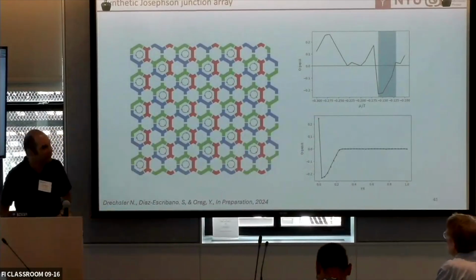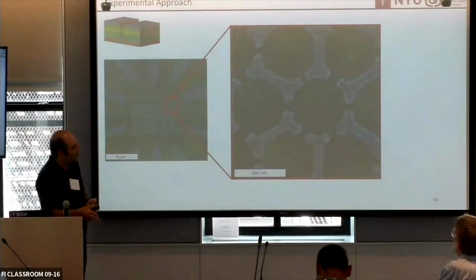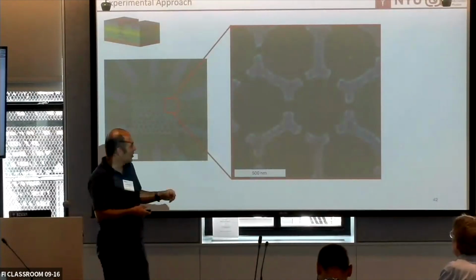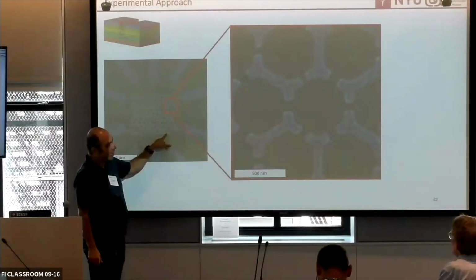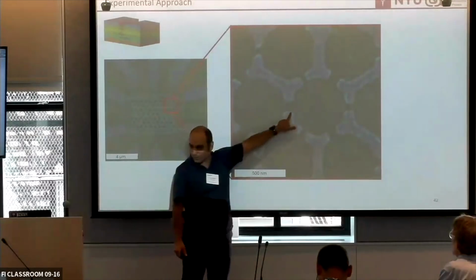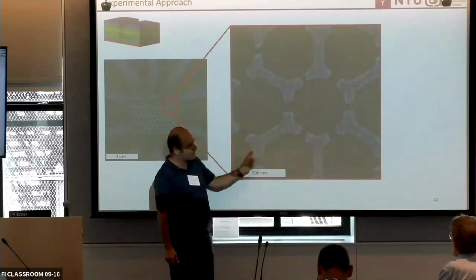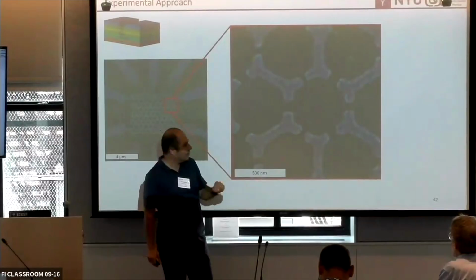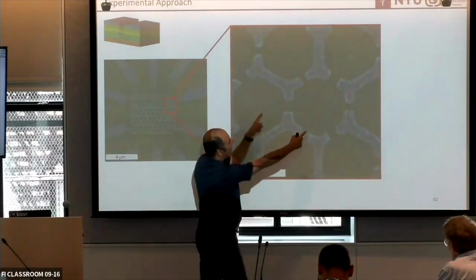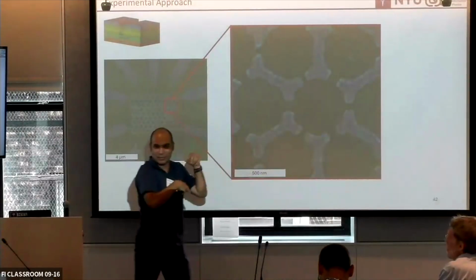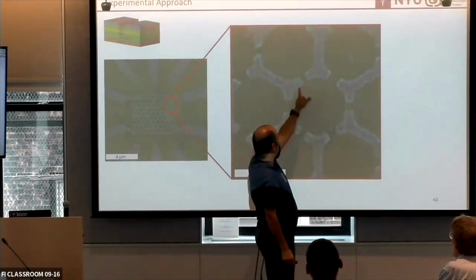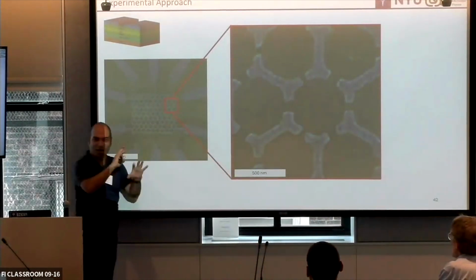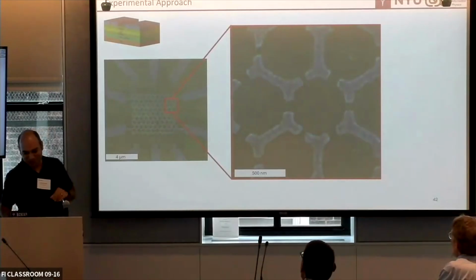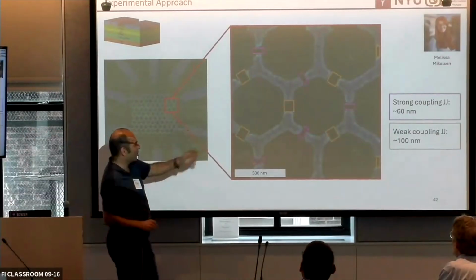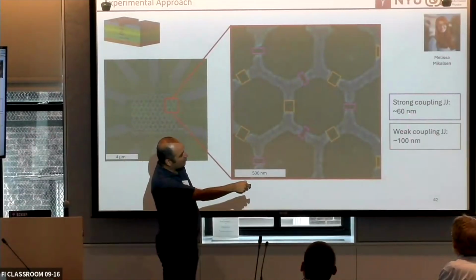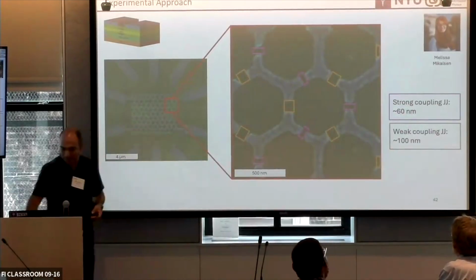So we basically got motivated by the theory. We are not exactly sure what we're going to see, but we were brave enough to go and just make these devices. This blue is the aluminum, and these are the dog bones we were just pointing at. If you look, the whole thing is less than 500 nanometers. Each hexagon fits in a 500 nanometer square. So I have 1, 2, 3, 4, 5, 6 Josephson junctions. These are kind of my big junction, small junction, big junction, and small junction. The big ones are 100 nanometers, and the small ones are 60.